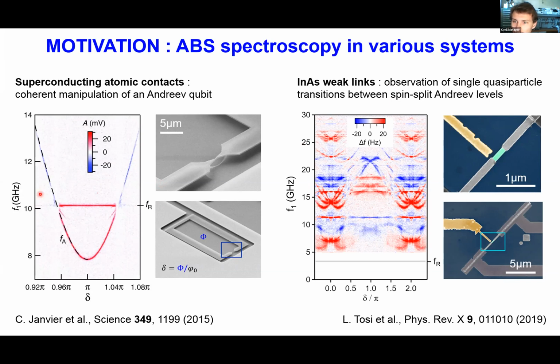However, with indium arsenide weak links, the signal that we measured has puzzled us for some time because it's quite different from the dispersive-like type of measurement that one usually performs and that we were used to when dealing with atomic contacts. So in this two-tone spectrum, for example, we had a pair transition anti-crossing with the resonator at 10 gigahertz. And so what's plotted here in color scale is the amplitude of one quadrature of the measurement field after homodyne detection, and is directly related to the resonator shift. And you can see that as the transition crosses the resonator, we go from red to blue, so from positive resonator shift to negative, which is exactly what we expect in dispersive measurements.